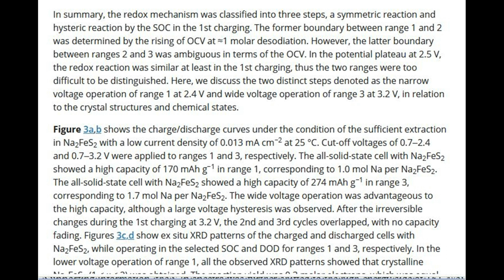Figure 3a, b shows the charge/discharge curves under the condition of the sufficient extraction in Na2FeS2 with a low current density of 0.013 mA cm-2 at 25 degrees C. Cut-off voltages of 0.7-2.4 and 0.7-3.2 V were applied to ranges 1 and 3, respectively. The all-solid-state cell with Na2FeS2 showed a high capacity of 170 mAh g-1 in range 1, corresponding to 1.0 mol Na per Na2FeS2. The all-solid-state cell with Na2FeS2 showed a high capacity of 274 mAh g-1 in range 3, corresponding to 1.7 mol Na per Na2FeS2.